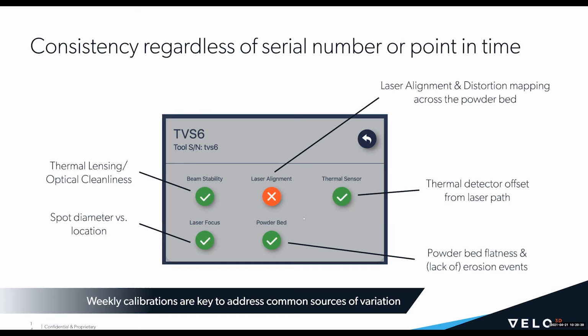So first off, we have a 3D topographical map of the powder bed that we often call the height mapper. We can use this to basically verify powder bed flatness. So this makes sure that you have a consistent layer of powder across the powder bed, which is important because the powder is your feedstock in a welding process. So you need to make sure you have a consistent amount of feedstock as you're welding. And then also we're able to look for erosion events. Erosion events can occur if there's a problem with the gas flow where it's basically eroding away the powder bed. So we verify for that as well.